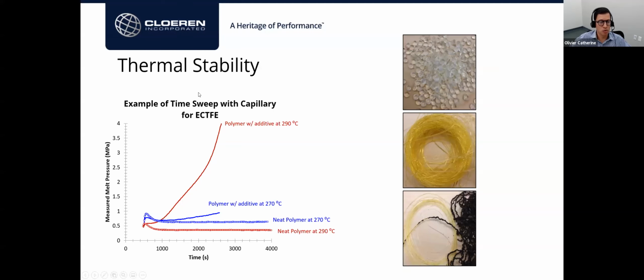So what we do is we measure pressure of a capillary flow over time for a long period of time, and we do basically some kind of time sweep. And if the material is stable, the pressure remains stable. So we did this at two different temperatures for the neat polymer, and everything is fine. And so we actually designed a die for this neat polymer, but then the customer was trying to extrude the material with additives and never told us, right?